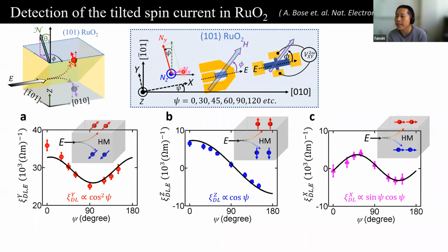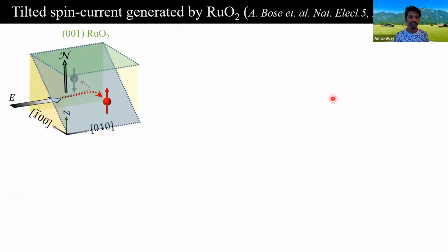We have 2 more questions in chat. The first one is, what can be the potential applications in devices or memories of this tilted spin current? Thanks for this nice question. In the first slide, I showed that the spin Hall effect is very good, but for the spin Hall effect we need an extra symmetry-breaking field just to tilt a magnet, or we need to do some other tricks, for example, having an antiferromagnetic exchange bias to achieve deterministic field-free switching. So this sort of tilted spin current could be a potential way to generate out-of-plane anti-damping torques, and that could be interesting for memory applications.